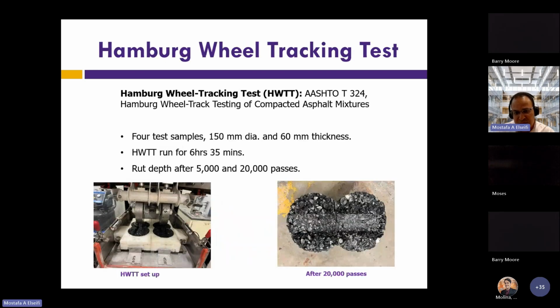The Hamburg wheel tracking test was conducted using AASHTO T 324. And again, for OGFC, because it has high air void, the state here requires to measure the rut depth after 5,000 passes. But NCHRP recommends to look at the rut depth after 20,000 passes. So we looked at both rut depths and we compared them between the different mixes.